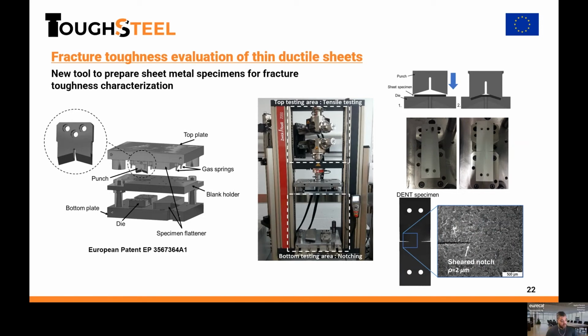So in this same research line, we developed this testing tool because we know these fatigue pre-cracking procedures are expensive and time-consuming and require special equipment. So at the industrial level, it's difficult to implement this fatigue pre-cracking operation. So we developed this rapid notching procedure to prepare sheet metal specimens and introduce really sharp notches, as you can see here, with a notch radius of about 2 microns by means of a simple shearing process. And we can obtain these really sharp notched specimens in a few seconds, and they can be used to evaluate the fracture toughness.